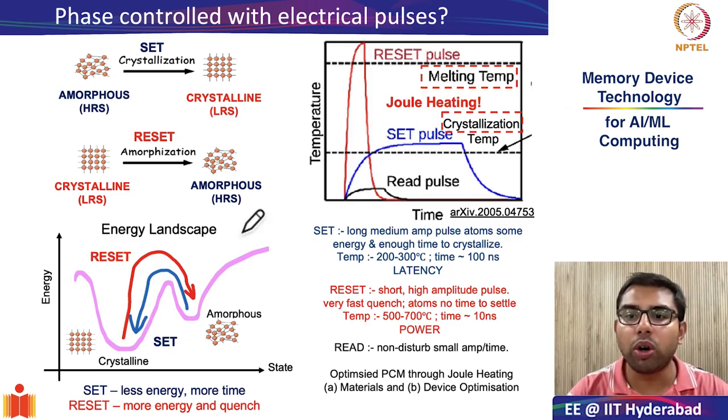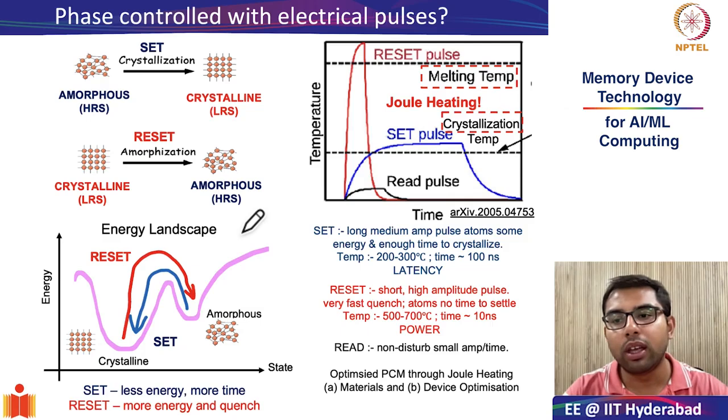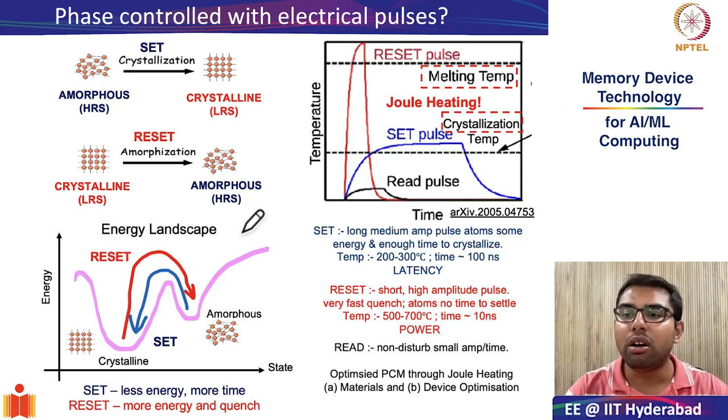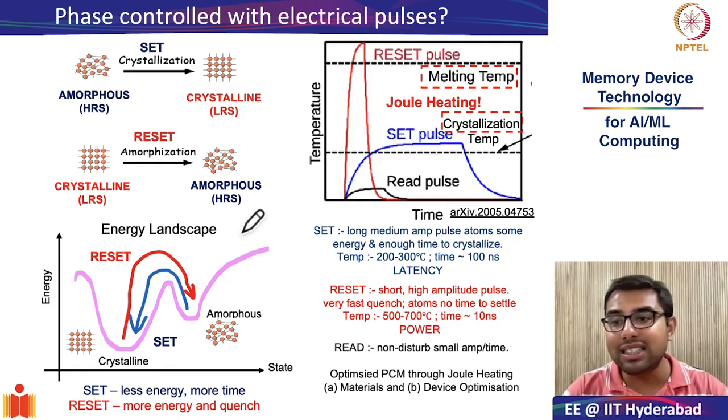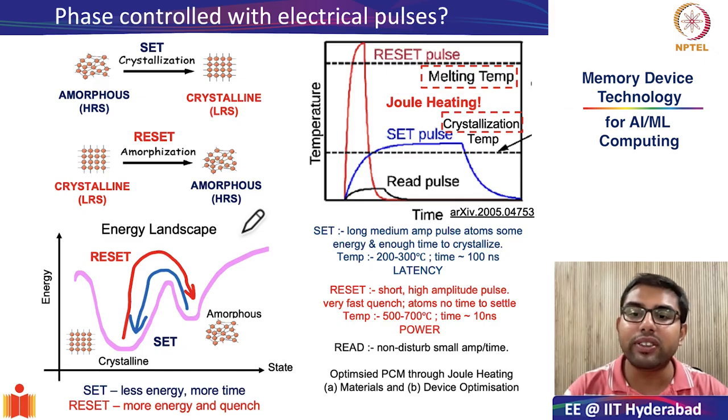Let us try to recall what we were discussing the last time around. We began with an understanding of different phases of solids as characterized by range of order, with the crystalline state having long range order and the amorphous state having the shortest range of order. We also saw that for the same material, the crystalline state has the lowest resistance and the amorphous state has much higher resistance. And that is due to the scattering of the charge carriers involved in transport.